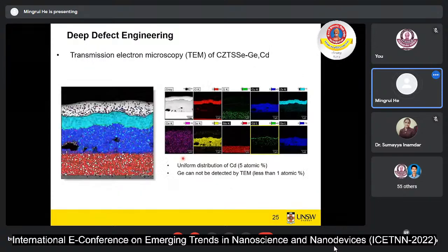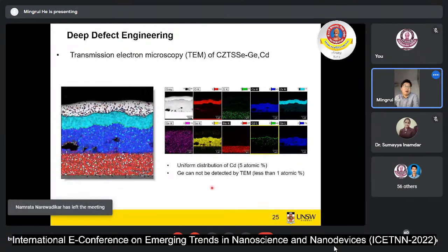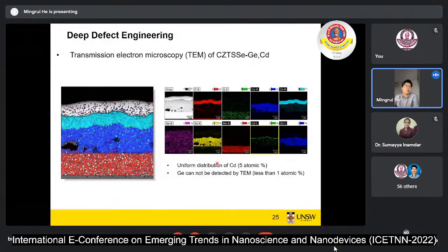First, of course, I checked to confirm whether I successfully incorporated both materials, germanium and cadmium. As we can observe, there is a weak signal of cadmium, which we calculate to be around 5 atomic percent. So yes, we succeeded in the cadmium alloying. Unfortunately, we cannot observe any germanium, but it is highly likely due to the resolution of the TEM. I also did the same thing with another technique, but I didn't put the figure in here. We found the germanium signal there, which means we also incorporated the germanium.